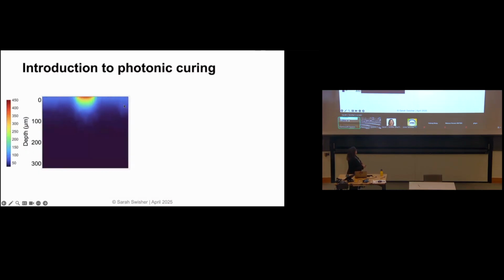Okay, so if we look at the depth here, again, this is looking through the depth of this glass substrate in this case, and what you can see is that up here at the top, you're reaching about 450 or 500 degrees right at the surface of that gate, and you do actually get a little bit of heat that's coming down into the substrate. And you would think that that would cause a lot of problems. But as it turns out, we've got enough of the substrate down here that stays very cool, right? This is about 30 degrees back here.